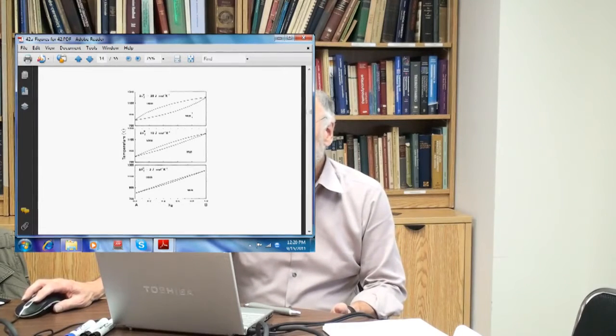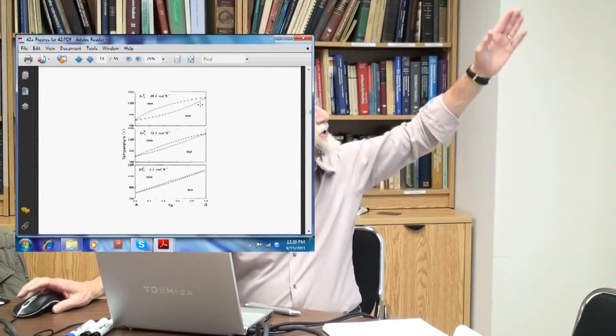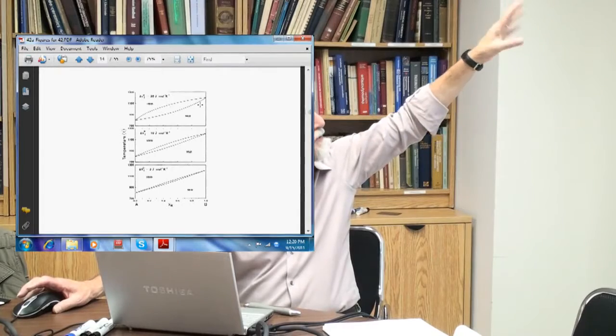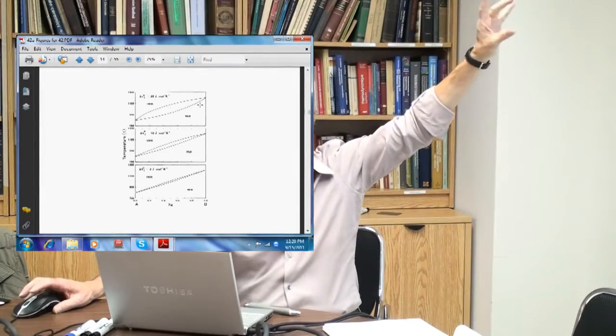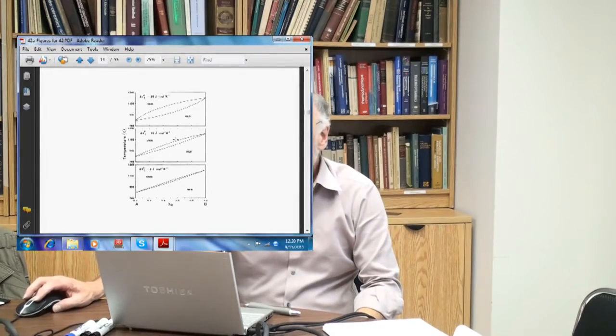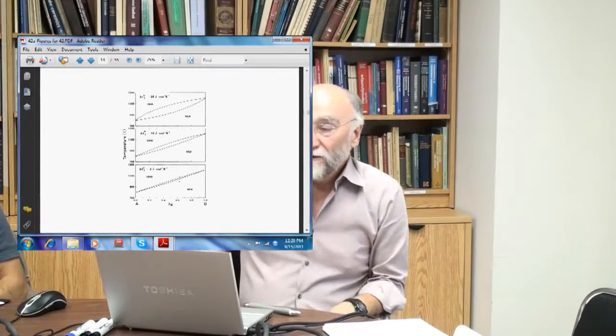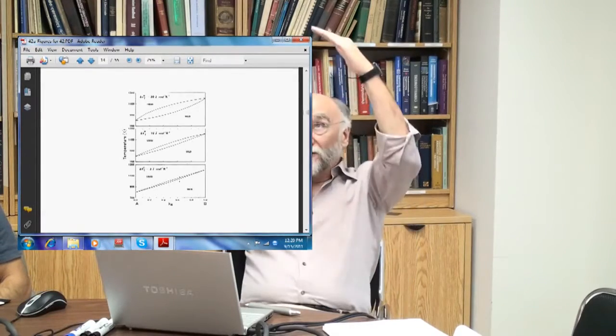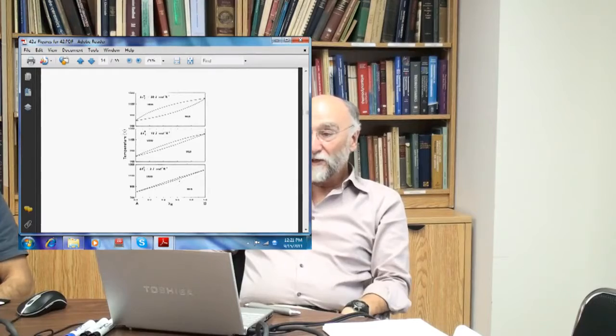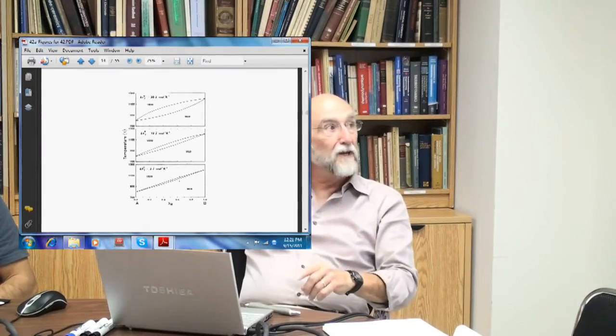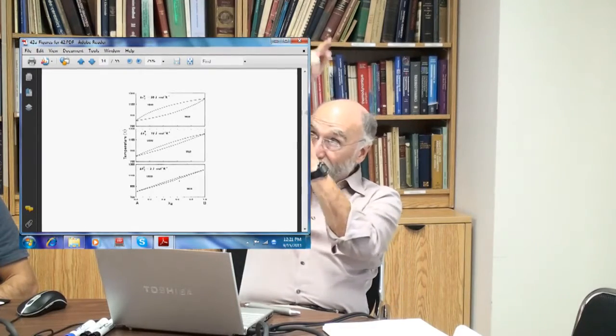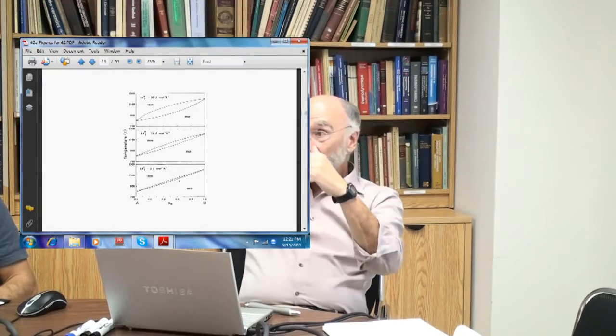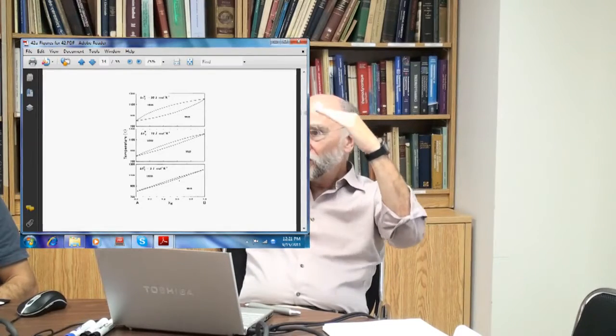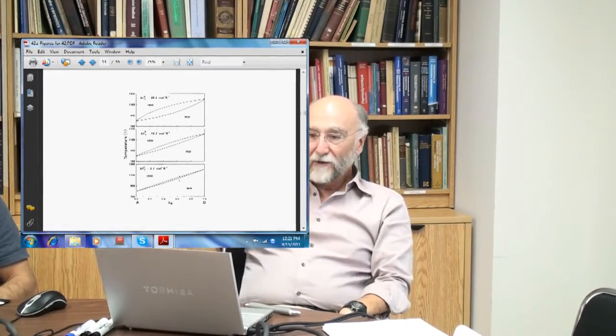The liquid and solid are still both ideal solutions. All that's changed is the entropy and the enthalpy of fusion have both been decreased by a factor. And you see the effect it has in the phase diagram. You can think about that at home. Think about those two curves coming through each other. The shape of the curves is the same. The Gibbs energy of mixing, which is the distance there, stays the same. It's just that the rate at which they're moving through each other is different, and it ends up this way.